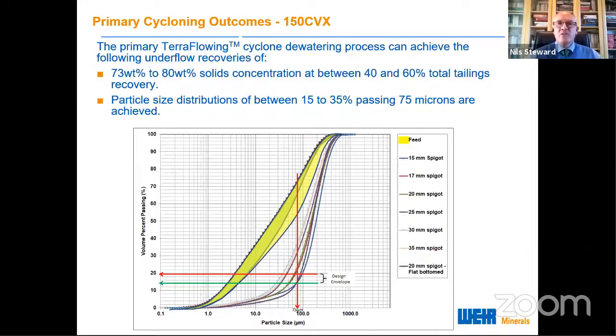microns. The reason I mentioned the particle size distributions is that when you're constructing a tailing storage facility embankment, the train of thought currently is that you want to have an underflow particle size distribution of 20% less than 75 microns. This is only a guideline. Obviously, your underflow product has to release the water. It has to be compactable. It has to achieve certain strengths. And all of that is a geotechnical assessment. But typically, 20% passing 75 microns.